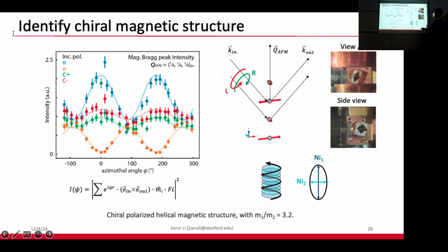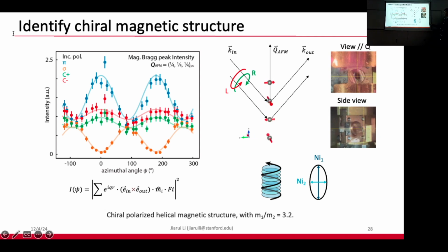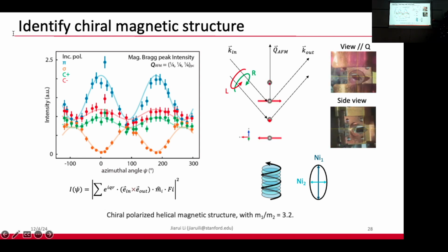And we took the measurements, shown here with different X-ray polarizations. We see that the magnetic Bragg peak intensity modulates as we rotate the sample systematically. And there are twofold rotations, with maximums and minimums. By fitting these azimuthal modulations of the magnetic Bragg peak intensities with some models, we can actually obtain the magnetic structure. And it's shown here that it is indeed a right-handed magnetic spiral. And looking from the top, the nickel 1 spins and nickel 2 spins are 90 degrees apart, with a factor of 3 difference in the magnetic moments.